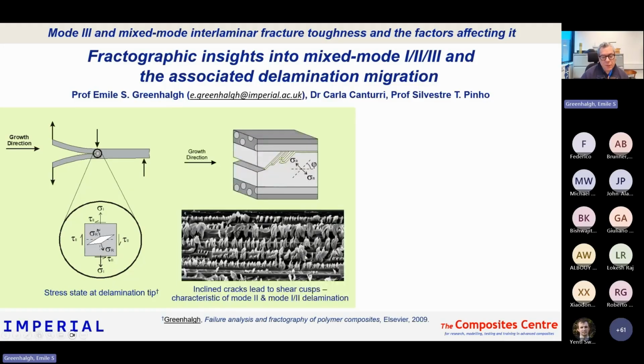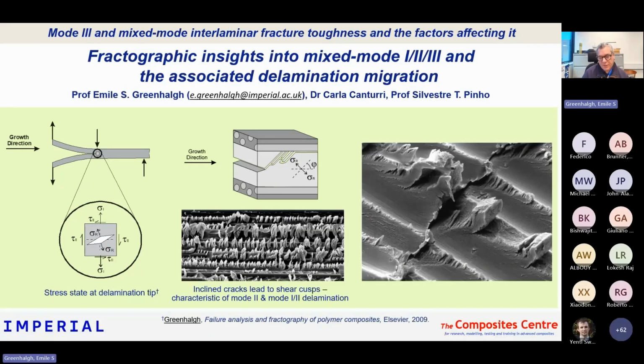So from a fractographic point of view, what we see on the fracture surface are these features called shear cusps, and these are very characteristic. If you look at a mode 2 or a mode 1-2 delamination, these are essentially these angled cracks which have developed. And the important thing that comes out of this is that these cracks drive, under these low mixed mode conditions, upwards through the laminate, as shown here. I've exaggerated the thickness of the interlaminar region to illustrate this cracking process. And then if you inspect these cusps and look at the angle at which the imprint of the cusp has developed, you can see that this angle actually relates to the mode mixity. So the higher the mode 2 component, the higher the inclination of these cusps. These are observations that we've made from looking at fracture surfaces in mixed mode 1-2 in unidirectional laminates.